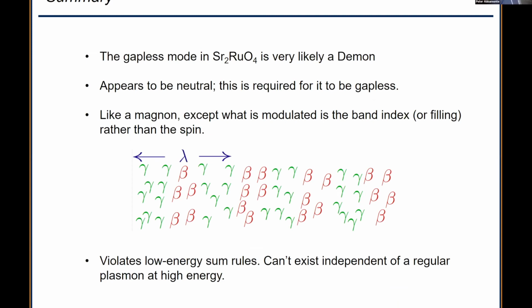So in summary, we've discovered a gapless mode in strontium ruthenate. It's highly reproducible. We saw it in quite a few measurements. My student Ali is extremely confident in this thing, and we think it's a demon. The reason we think it's a demon is two things. First of all, it's gapless. The only way a charge collective mode can be gapless is if it's neutral, at least in the long wavelength limit. And it does in fact appear to be neutral in the sense that it violates the F sum rule in the correct way.